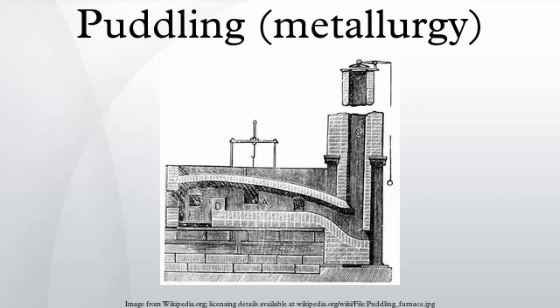The alternative to refining gray iron was known as wet-puddling, also known as boiling or pig-boiling. This was invented by a puddler named Joseph Hall at Tipton. He began adding scrap iron to the charge; later he tried adding iron scale. The result was spectacular in that the furnace boiled violently — a chemical reaction between the oxidized iron in the scale and the carbon dissolved in the pig iron. To his surprise, the resultant puddle ball produced good iron. One big problem with puddling was that almost 50% of the iron was drawn off with the slag because sand was used for the bed. Hall substituted roasted tap cinder for the bed, which cut this waste to 8%.